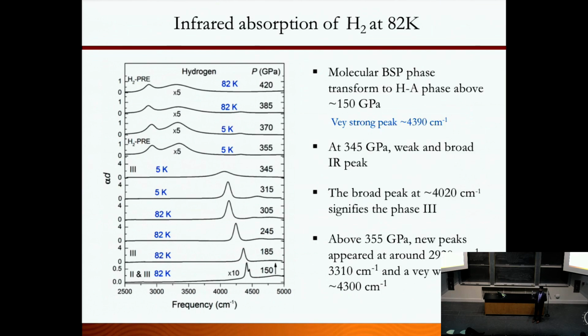So while we were doing this, we observed a new phase transition. I'm going to give you a little idea of how we determined the new phase. This is the frequency, and this is the absorption you're seeing here. I mentioned that to determine a new phase transition in a material like hydrogen, you track the vibron. If you see modes disappearing or new modes appearing, that indicates a change of symmetry and a new phase transition.